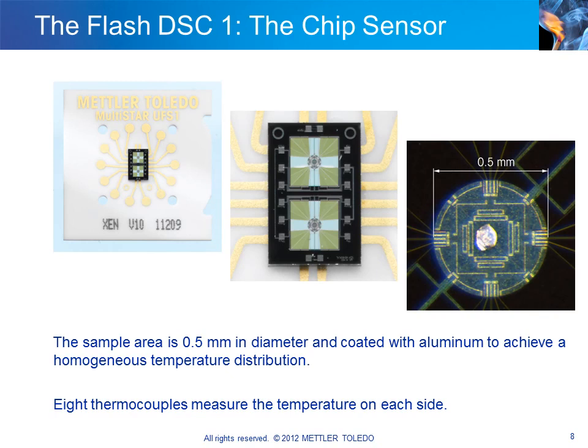The picture on the right is an enlarged view of the sample side of the sensor containing a sample. To achieve a homogeneous temperature profile and to simplify sample preparation, the active part of the membrane area with a diameter of 0.5 millimeters is coated with aluminum. The 8 thermocouples and 4 resistance heaters are also visible.